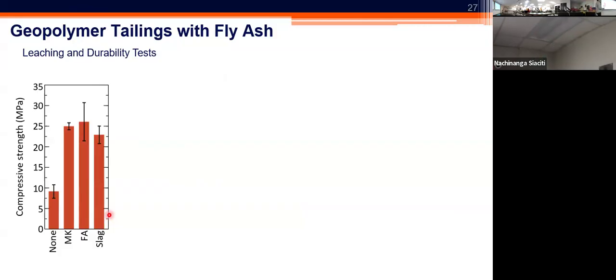Before I show you some of the results, I'd like to again make the point that in some scenarios, your mine tailing in its original form may only give you fairly low levels of strength for your geopolymer bricks, maybe in the order of 10 megapascal. But it may only take 15% of different types of waste, supplemented with, for example, metakaolin, fly ash, and slag. In all of those cases, adding only 15% of your solids in the form of those supplements can double or triple your strength values. So that's a good reminder that even if you document some deficiencies in strength, the solution can be fairly simple and inexpensive. So what did we do to evaluate better the potential for immobilization of the heavy metals and contaminants?